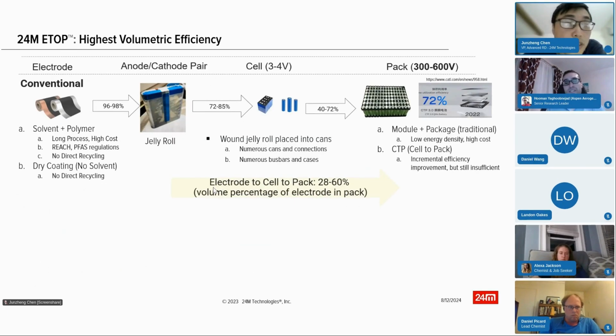So first thing is we found that currently in the market, there is one way to have the cell as high energy density as you can. Basically when you put the electrode into the jelly roll, and then you put the jelly roll into a can or into the pouch. Then the can and pouch become a module pack. So the best scenario they are currently showing is around 72% with the CTP structure.